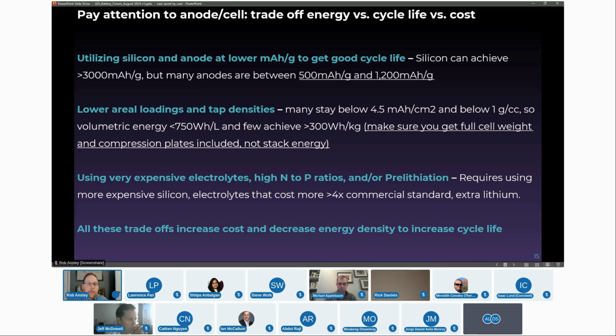Also, some companies really have to use a high N to P ratio. And what does that do? That basically runs your silicon less hard. So let's say you have 100% silicon, right? And after formation, you got 3,000 milliamp hours per gram. If you run an N to P of 2 to 1, you're only rating your silicon at 1,500. If you do an N to P of 3 to 1, you're only rating your silicon at 1,000 milliamp hours per gram. And that's how you get cycle life. You just rate it lower and lower and lower. All of a sudden, your cycle life looks better and better. So what are you doing? Trading energy for cycle life, just like every other chemistry.